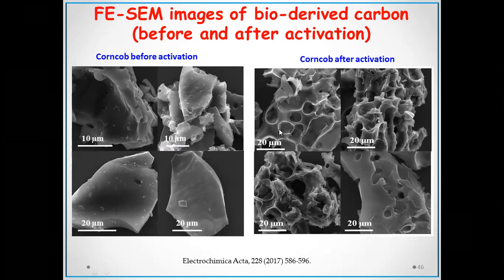This is a scanning electron microscope image of the corn cob derived carbonized carbon. You can see there is a 20 micron size crystal, a very big crystal. Whereas when you treat with KOH during activation, it makes a lot of punctures, or some holes, on this. So obviously we produce high surface area carbon. These pores can easily allow the electrolyte to penetrate, since we have both microporous as well as mesoporous, and also some amount of macroporosity. The combination of these micropores, mesopores and macropores is very essential for high performance supercapacitor activity.